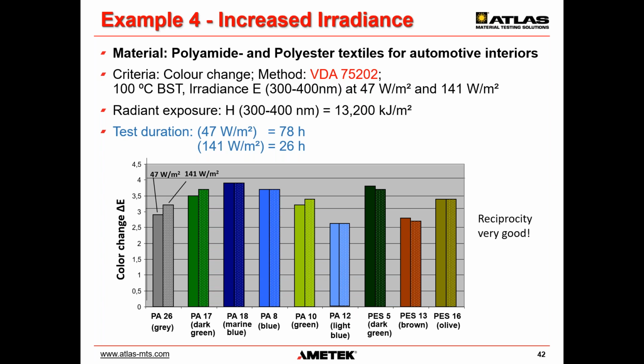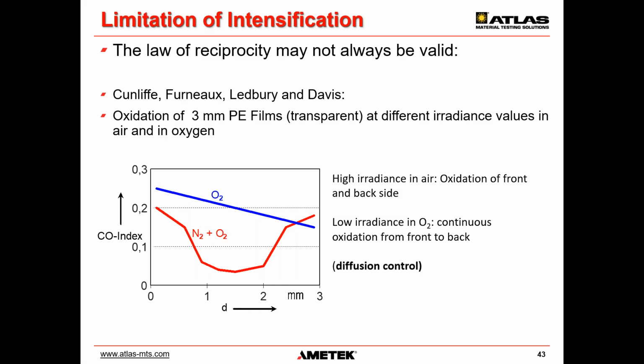My parameter of interest in all these cases was color change, which is primarily a result of photochemical reaction which destroys the colorant. And these reactions tend to primarily be photon dependent. When you get into physical parameters such as cracking, adhesion loss, or tensile strength, which are often a combination of UV exposure combined with temperature and/or moisture cycling, the law of reciprocity likely will not be followed quite as well, because there are a lot of non-photon reactions occurring in polymer degradation. Important to keep in mind. The law of reciprocity may not always be valid.